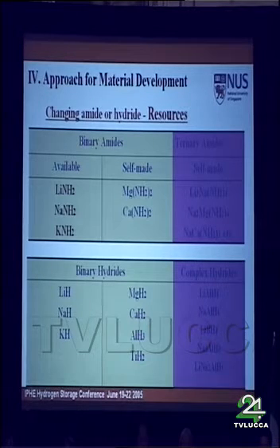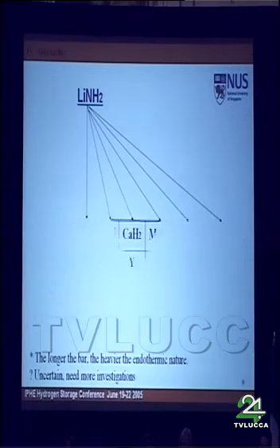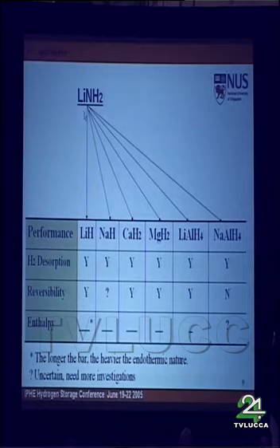Thus, we can combine different amides and hydrides and look at the chemical reaction between these two chemicals. For example, if we fix lithium amide and react it with different hydrides, we will find hydrogen desorption from such a chemical reaction. In such reactions, we also look at the reversibility and the enthalpy of the reaction, whether it is endothermic or exothermic. Based on our recent experimental results, in those reactions there is hydrogen desorption, some of them are reversible, and most of them are endothermic.